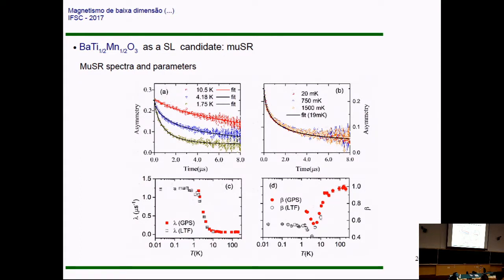So, of course, I still need to say something about the spin liquid. You have to go with microscopic and thermodynamic properties, so we resort to muon spin rotation (μSR) measurements. Here I'm showing the measurements that we got from the high temperature sector. We have measurements up to 150 Kelvin, and this is how the spectra look for the high temperature data. As you can see, below 1.5 Kelvin we can almost fit it with a single exponential, as reflected by the fact that the extracted parameters become essentially constant. And GPS and LTF are two different spectrometers. You have to change the spectrometer, but you take some points for superposition.